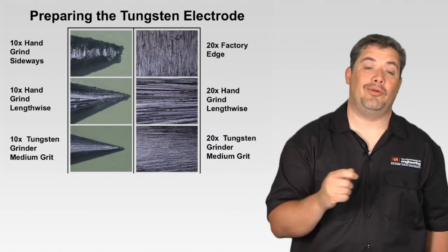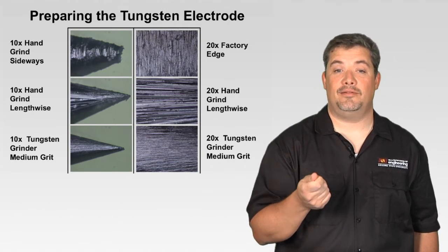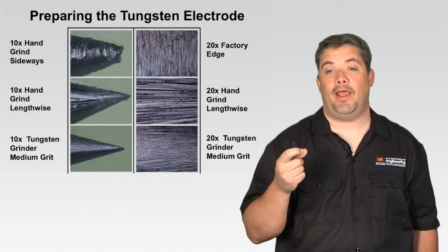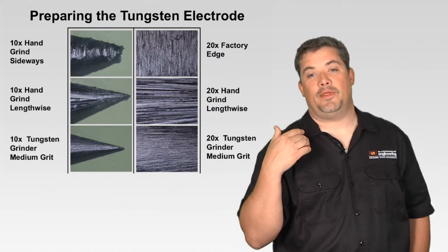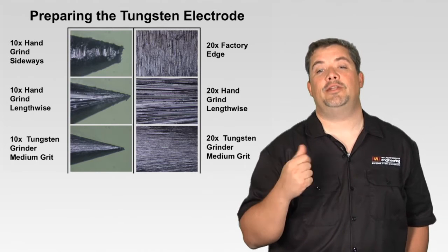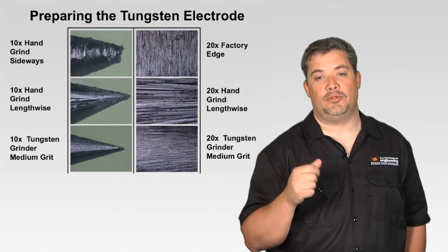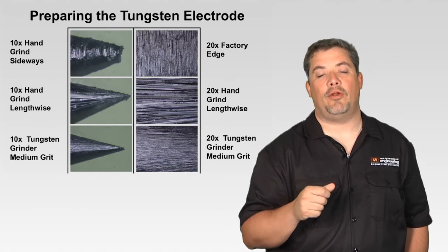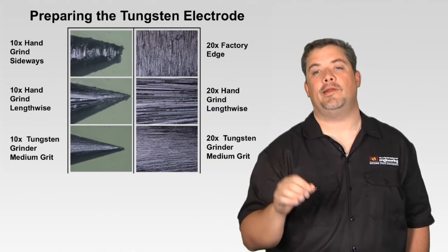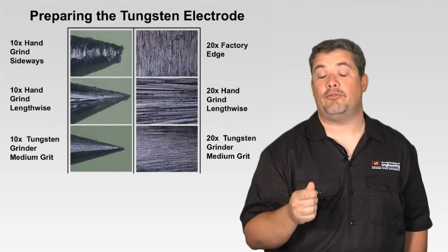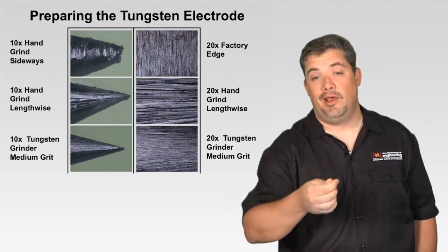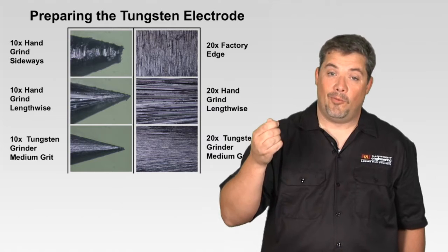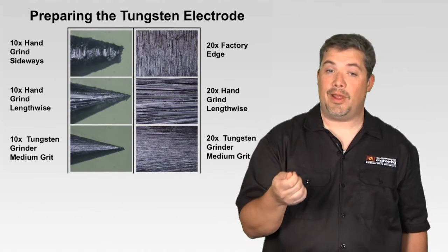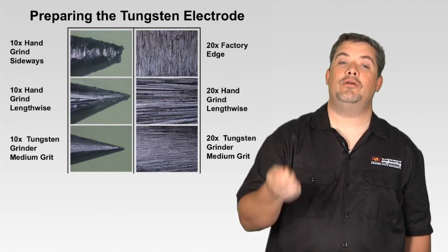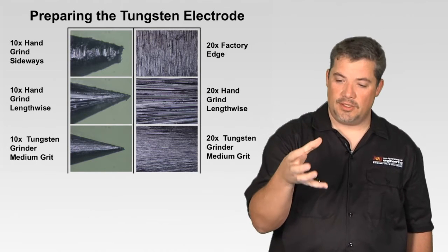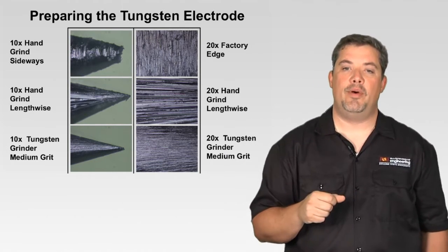Using a tungsten grinder with its medium grit, you can see that so much cleaner, the burrs are gone, and at that 20x magnification, you can see that it's even a smoother surface yet. Imagine the fine grind, it'd probably be just almost a mirror. But we use diamond ground tungsten grinders specific for tungsten to ensure that we don't have contamination from other things. So when I just take a tungsten and I sharpen it on any grinding wheel, whatever that grinding wheel was grinding might get embedded in my tungsten. So having a dedicated wheel or a dedicated tungsten sharpening tool is best.